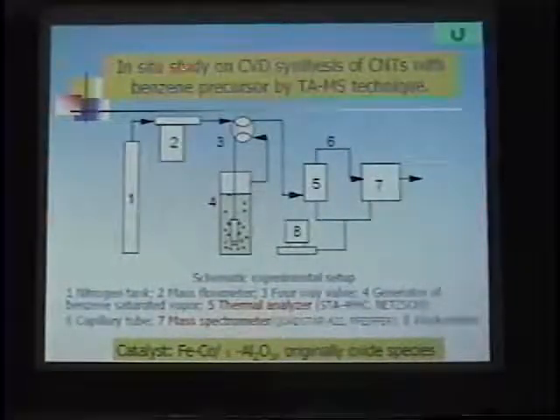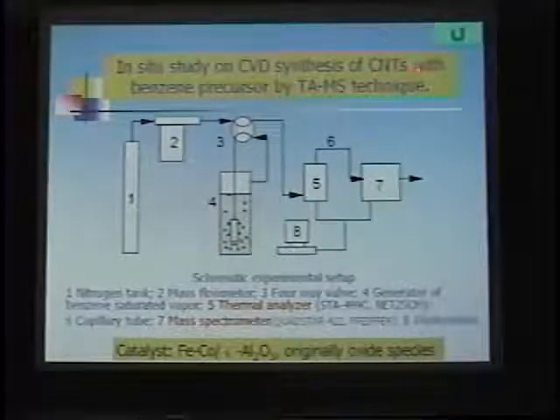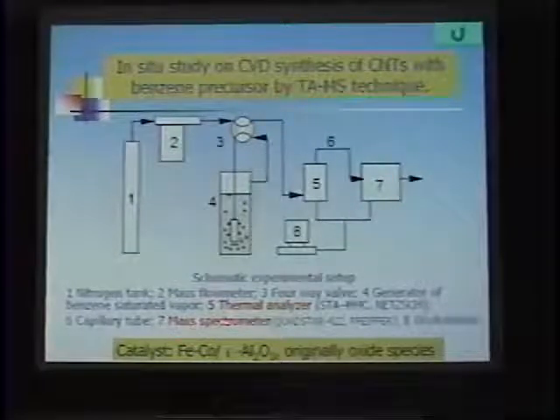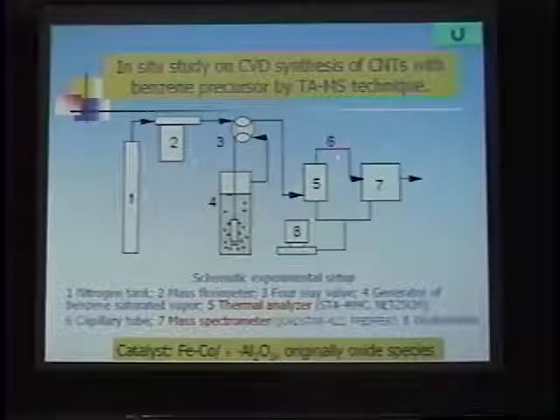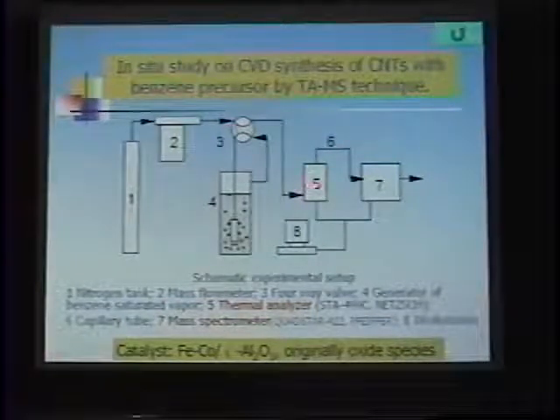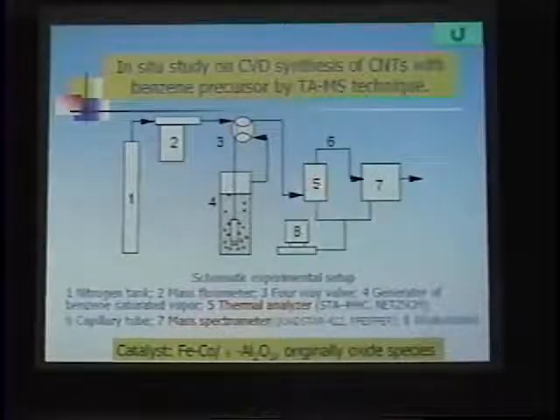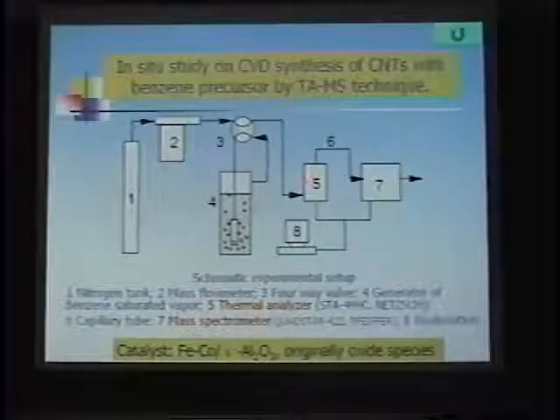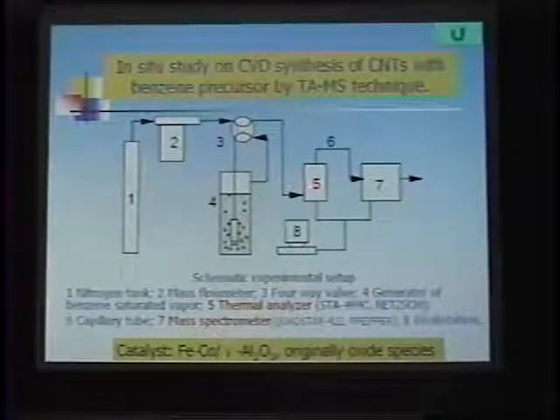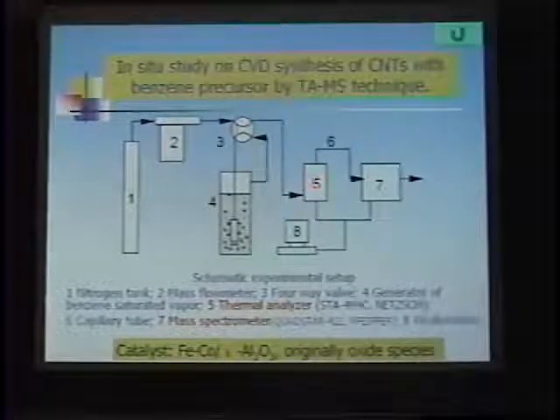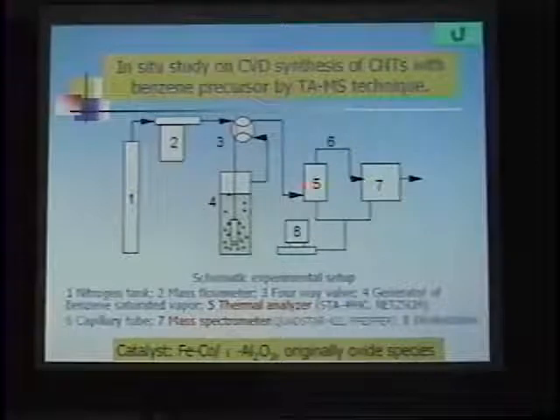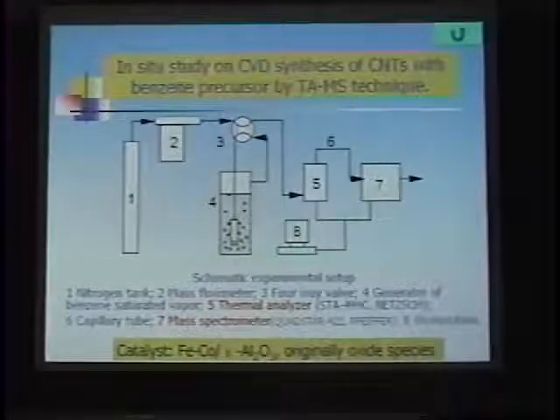Then we made an in situ study on the CVD synthesis of carbon nanotubes with benzene precursor by thermal analyzer and mass spectral technique. The 5 is the thermal analyzer, the 7 is the mass spectrometer, and the 6 is the capillary tube. The benzene molecules were introduced to the thermal analyzer. The catalyst was put into the oven of the thermal analyzer, so the changing behavior of the catalyst and the weight gain during preparation could be monitored by the thermal analyzer, and the released gaseous species could be analyzed online by the mass spectrometer. By integrating such information, the growth mechanism could be figured out.